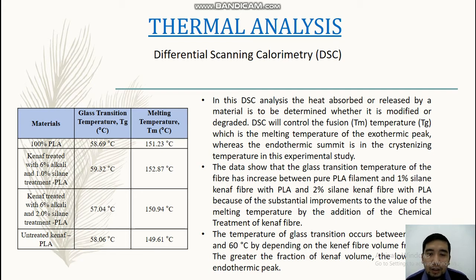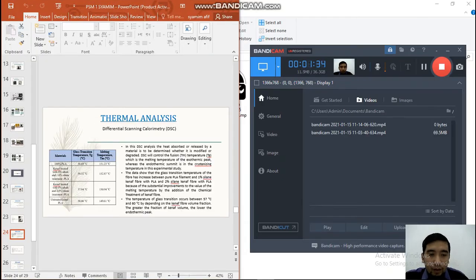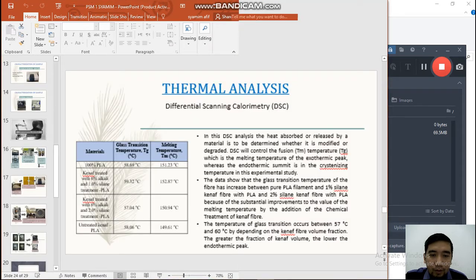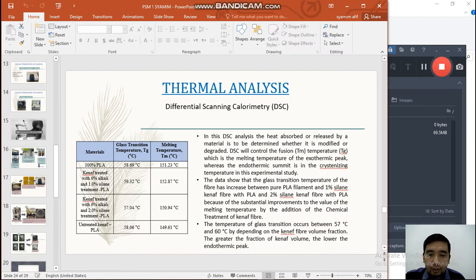The data show that the glass transition temperature of the fiber has increased between pure PLA filament, 1% silane Kenaf fiber with PLA, and 2% silane Kenaf fiber with PLA, because the temperature moves to the value of the melting temperature by addition of the chemically treated Kenaf fiber. Okay, the glass transition temperature occurs between 57 degrees Celsius and 60 degrees Celsius, but depending on the Kenaf fiber volume fraction. The greater the fraction of the Kenaf volume, the lower the endothermic peak.